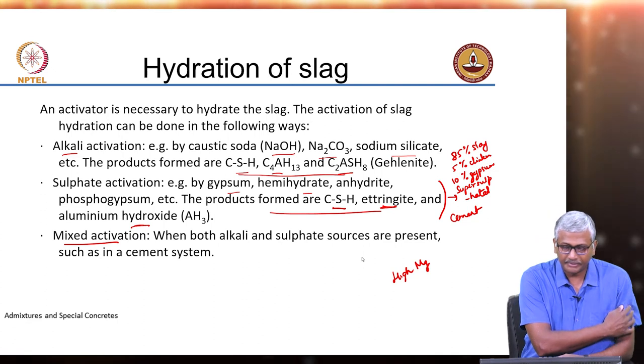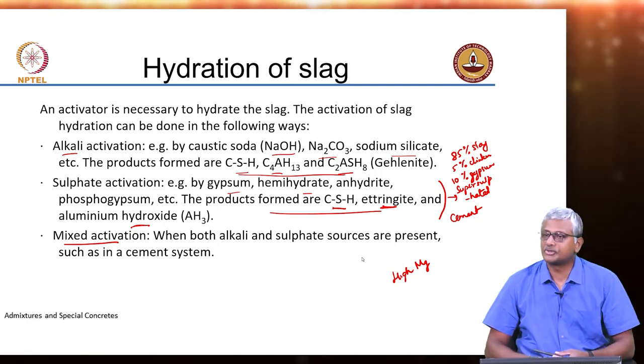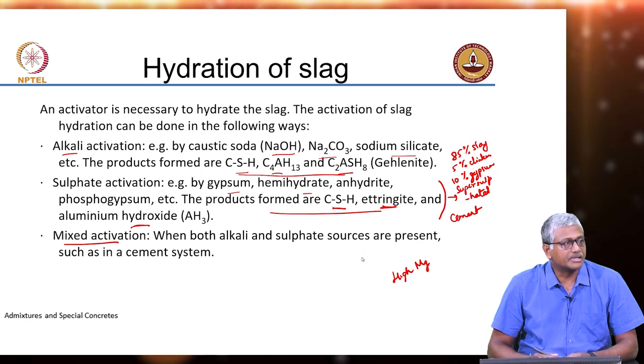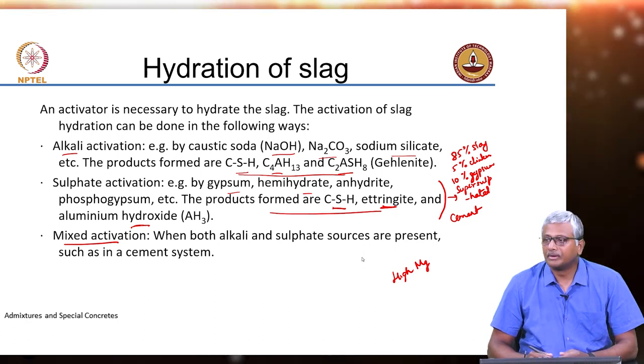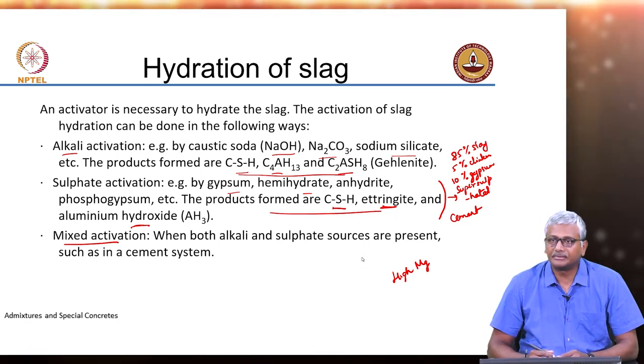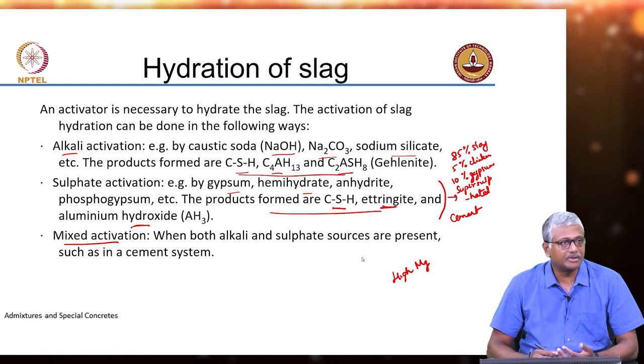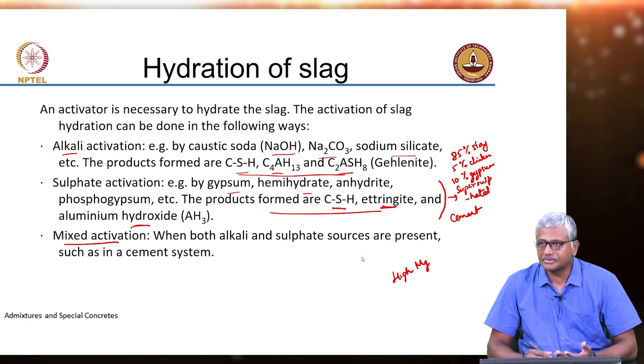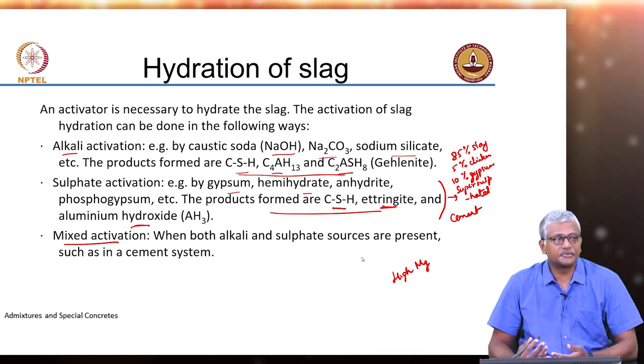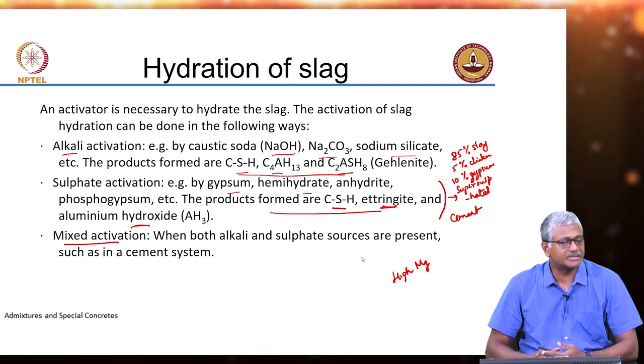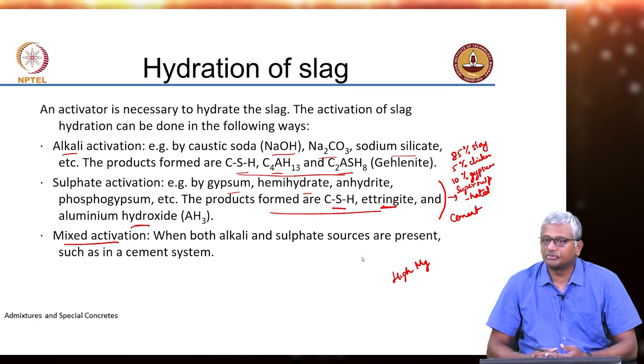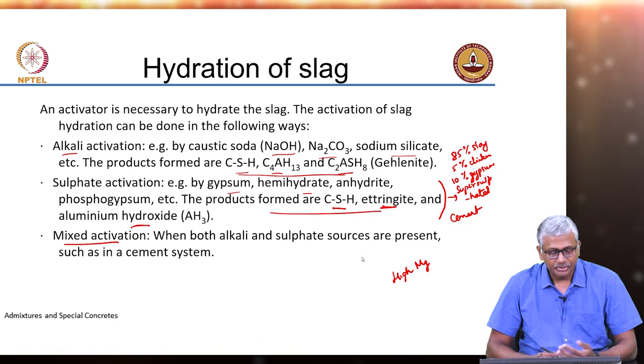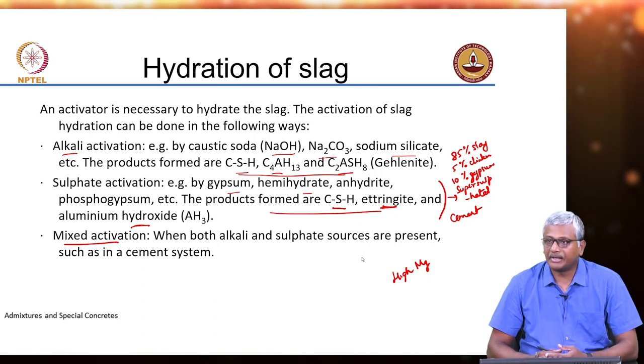Good morning all. Let us resume our discussion on ground granulated blast furnace slag. In the last class we were talking about the hydration of slag. Hydration is enabled by activation. This activation can happen with the help of alkalis or sulphates, but when slag is used in combination with cement, the activation is with the help of both alkali and sulphate provided by the cement. So mixed activation is what we typically have.